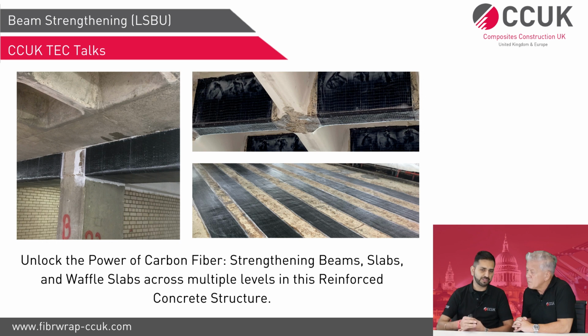The reason for strengthening was that this is a typical 1960s waffle floor construction. So they have the ribs running in both directions, but for some strange reason there was very minimal or no reinforcement in the transverse ribs. So for that reason they were treated as one-way spanning T-beams in a series. So we strengthened them at the underside by applying a carbon fibre plate system. The reason we used the plate there is that the ribs were only 100 millimetres wide. So if we cut the fabric to that width, we may end up with a lot of waste. So for that reason, a plate was used, which was 100 millimetres wide off the shelf.